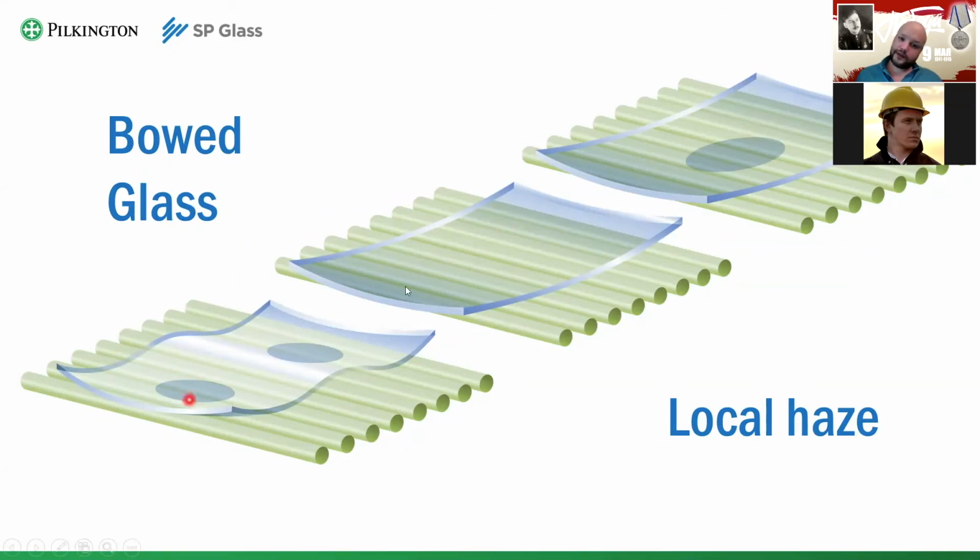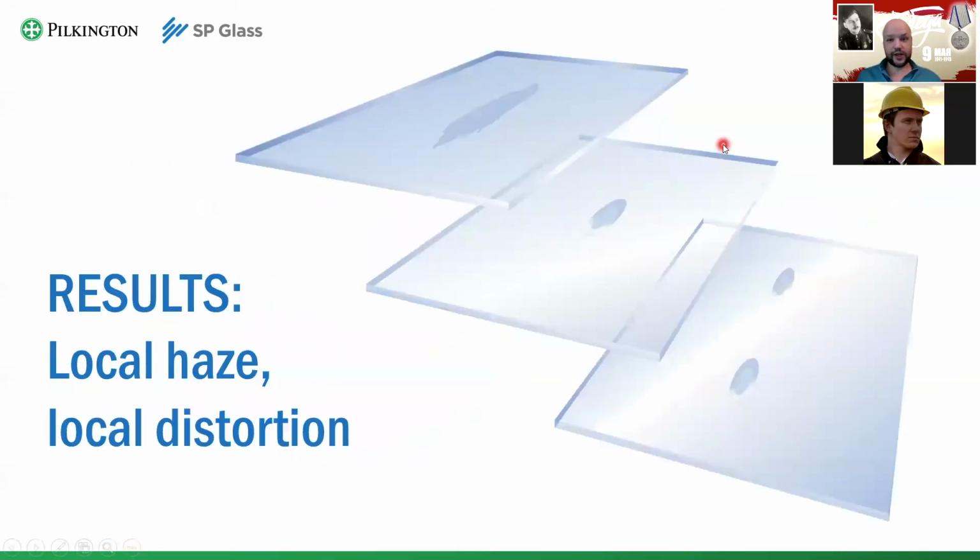And all of this glass bending in the heating chamber can cause you these types of defects. First, central distortions, one or two, or in very rare cases, even three. To give you an idea, I'll just take a sheet of paper and bend it in the center.